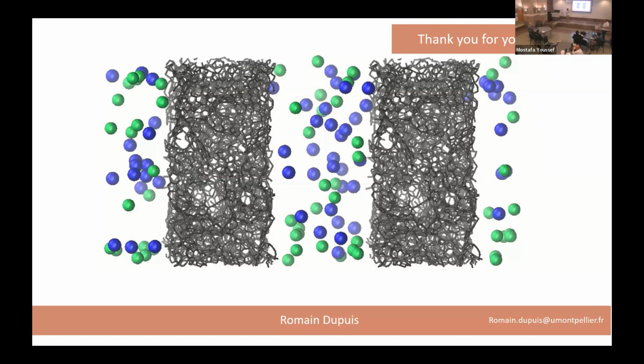So we have different kinds of structures, but the structures we use, like these porous electrodes, are made by a reverse Monte Carlo approach. And the idea is to try to have the correct porosity compared to the experiment, and to have the correct radial distribution functions as well. Okay, so you are building the defect in the graphene using Monte Carlo? Yes. I mean, they are not directly put inside, but they are in the pair distribution functions.